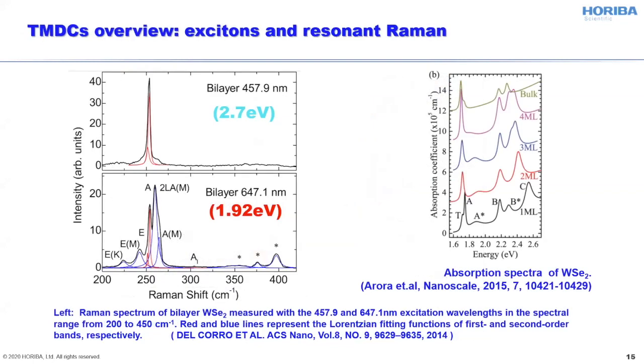Okay, and another interesting thing, if we come to an important class of these two-dimensional semiconductors, namely transition metal dichalcogenides, it is important to mention that most of the optoelectronic properties in these materials are mediated by excitons, which happily survive at room temperature because of huge binding energy. Therefore, these materials feature a number of excitonic resonances, which allows in turn to provide resonant excitation conditions for Raman spectroscopy. And when we hit one specific resonance, we can see many more Raman peaks in our Raman spectrum compared to non-resonant excitation.